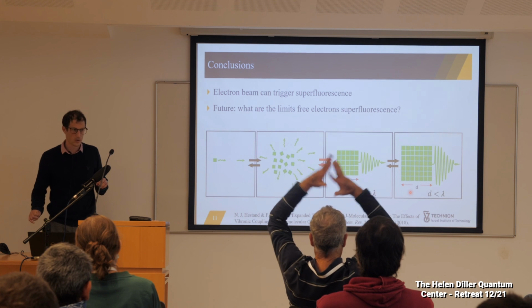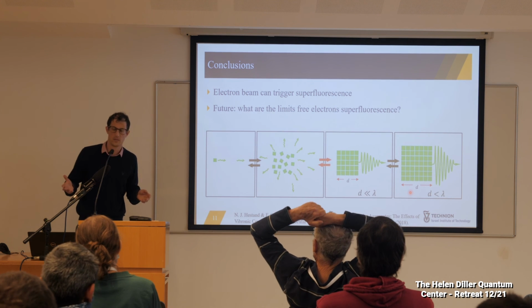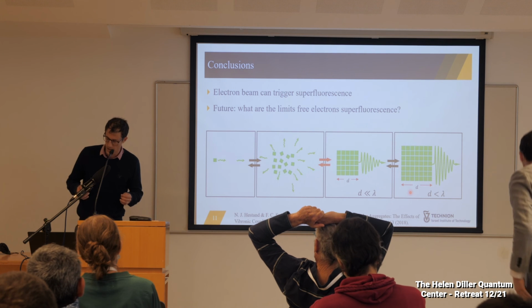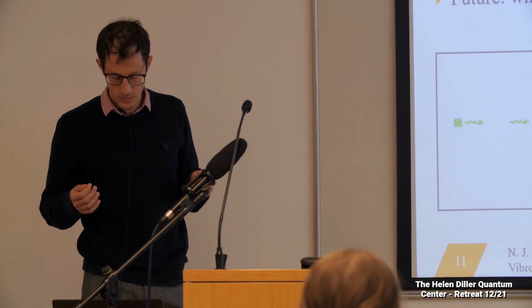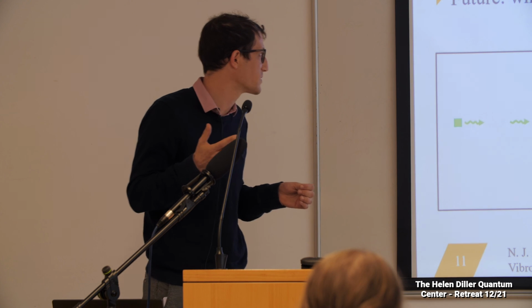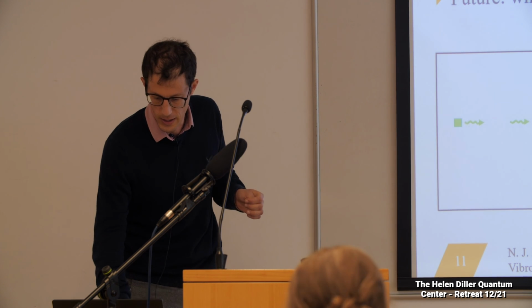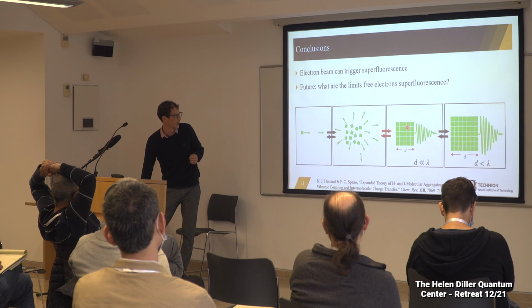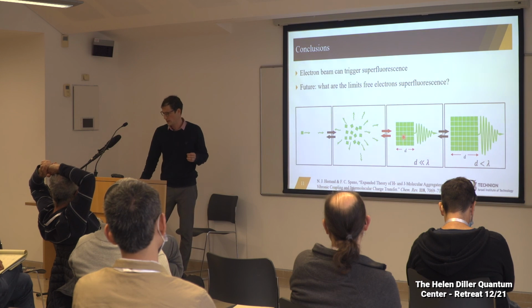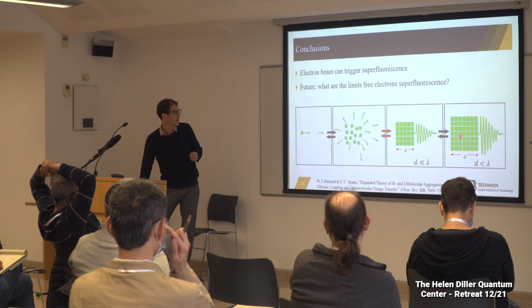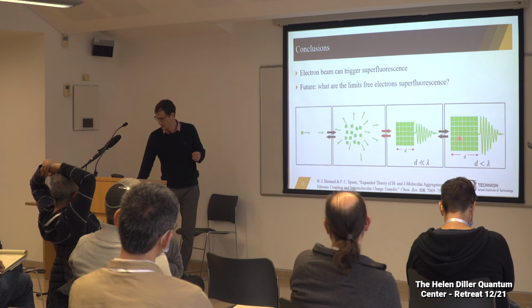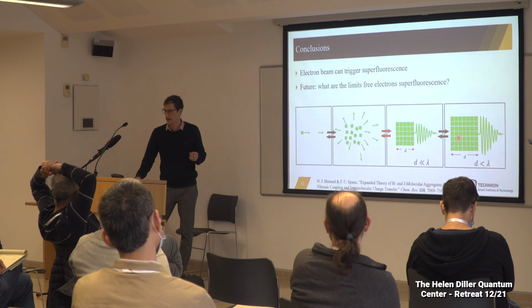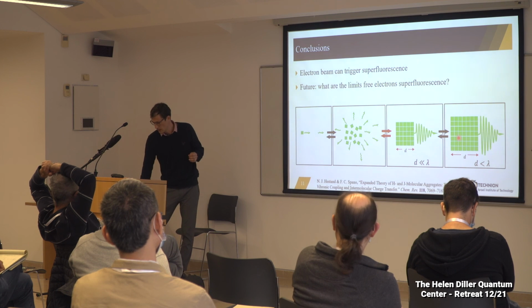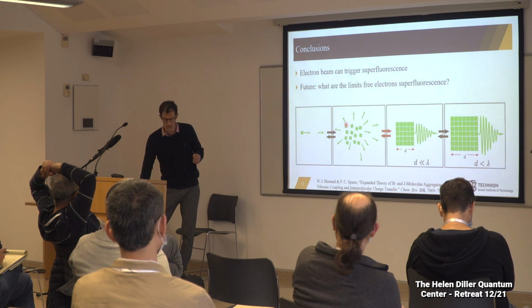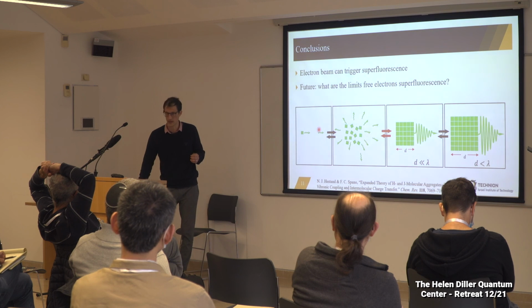So our conclusion is that the electron beam can, and we show it here experimentally, trigger superfluorescence. In the future, we want to test what the limits are for free electron superfluorescence. We saw that we can go from here to here with maybe coupling 5 quantum dots. Can we go higher, to more quantum dots participating in the superfluorescence, and get higher enhancement? And also, can we go to the other limit and measure cathodoluminescence from a single quantum dot?